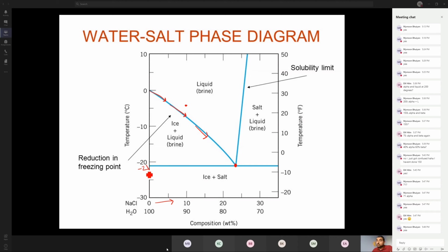If the temperature is really cold, let's say if we had a day with -30, the phase diagram says you have ice and salt. So you will spread the salt on the driveway and it will do nothing. It will just sit on top of the ice because the phase diagram says at -30, there is no liquid phase. You will have salt and ice. But if it was a little bit warmer, if it was -15, for example, then when you put a little bit of salt, you will have ice and liquid. It will turn into a slushy mix.